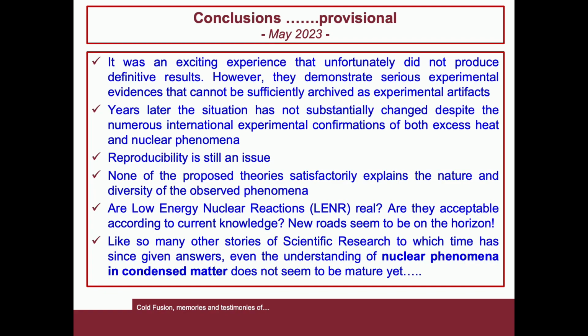Provisional conclusions, May 2023. It was an exciting experience that unfortunately did not produce definitive results. However, they demonstrate serious experimental evidence that cannot be sufficiently archived as experimental artifacts. Years later, the situation has not substantially changed despite the numerous international experimental confirmations of both excess heat and the nuclear phenomena. Reproducibility is still an issue. None of the proposed theories satisfactorily explains the nature and the diversity of the observed phenomena.